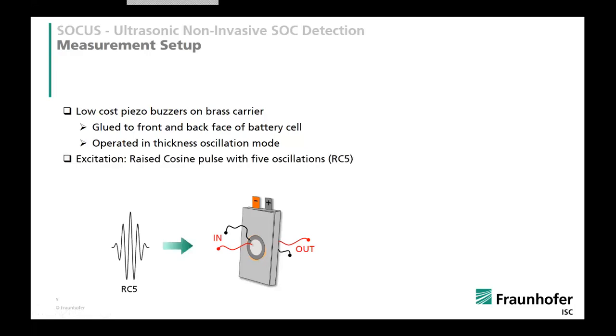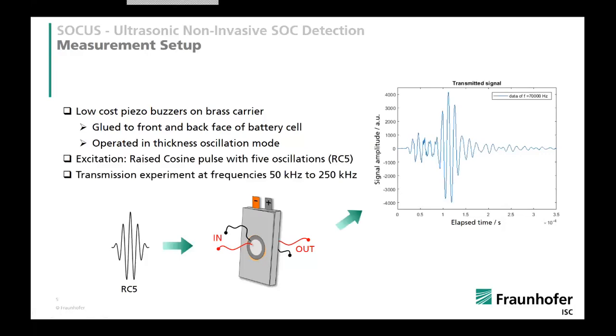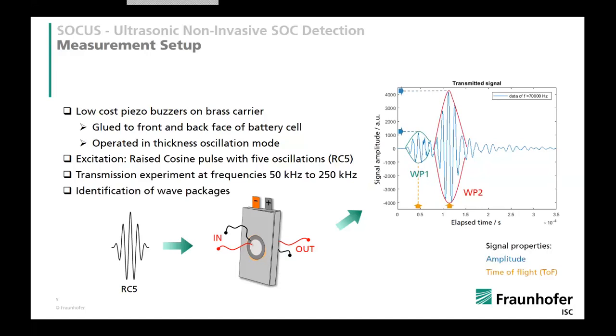What we used is quite basic signal processing methods. We use here a raised cosine pulse with 5 oscillations for the excitation, and we analyzed, in most cases, 2 waveforms, and we used transmission frequencies between 50 kilohertz to 250 kilohertz. And the analysis of the transmitted waves is quite simple. First, you have the time of flight, so the time between exciting the wave and then measuring the 2 wave peaks, and the other is, of course, the amplitude of the measured waves.